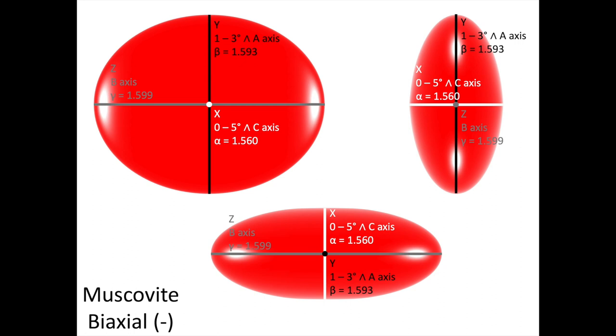For muscovite, the B crystallographic axis aligns with the Z direction through our optical indicatrix, which is associated with refractive index gamma. Our C crystallographic axis varies between 0 and 5 degrees off of our X direction through our optical indicatrix, and our A crystallographic axis varies between 1 and 3 degrees off of our Y direction through our optical indicatrix. Remember, the angle between our A and C crystallographic axes is 95.5 degrees. So here is a representation of how our crystallographic axes and our optical indicatrix line up. And as you can see, this is a bit complicated.